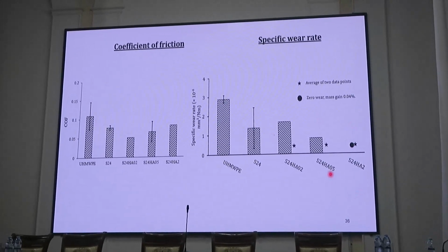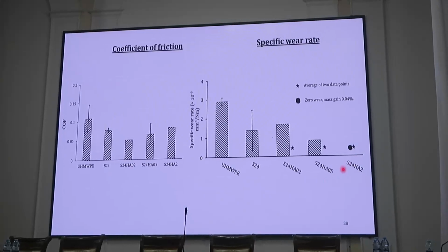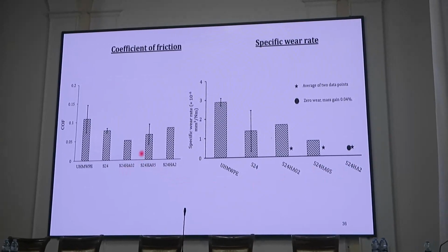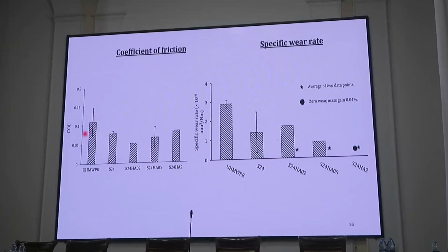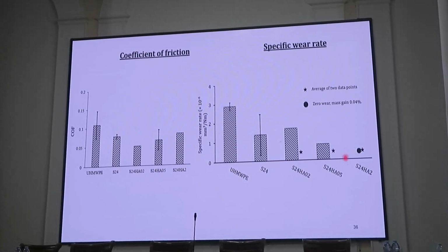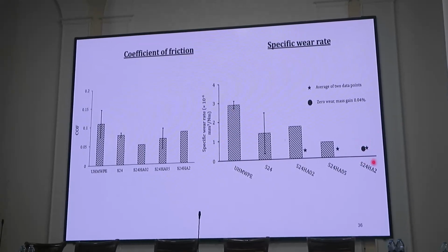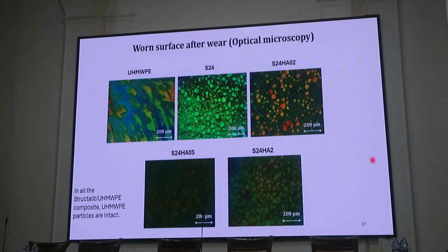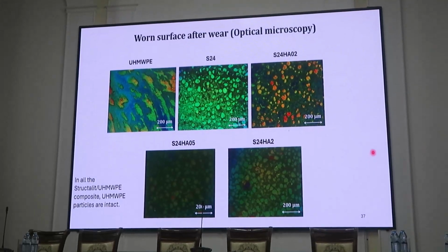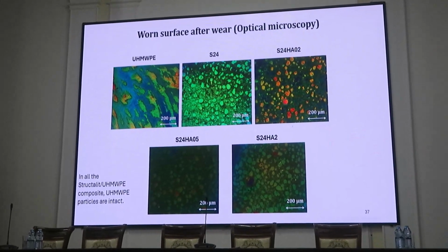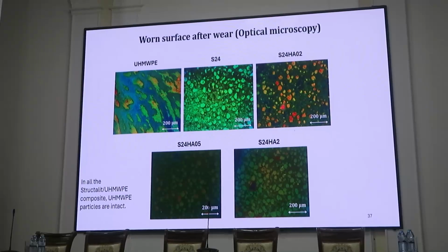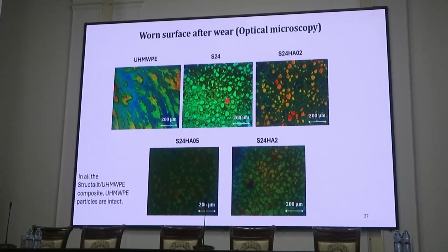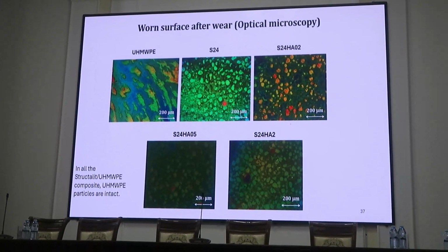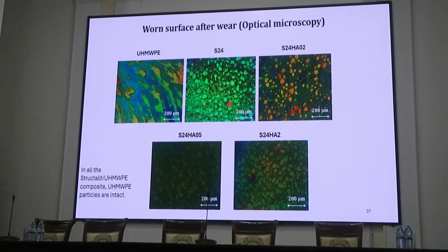This one is with HA, hydroxyapatite, and you can see the coefficient of friction is quite comparable to UHMWP, and the wear is very, very low. In fact, in some cases, you may not be able to even measure the wear. And looking at the microstructure, we have seen that the UHMWP particles are intact inside. They are not something which will come out of the matrix, so that is good.